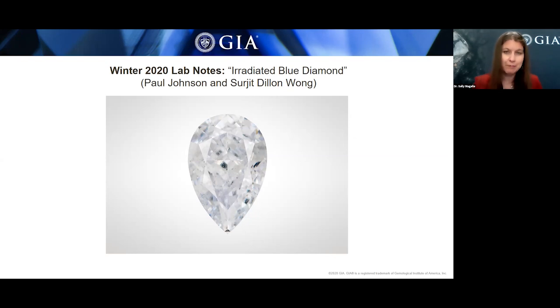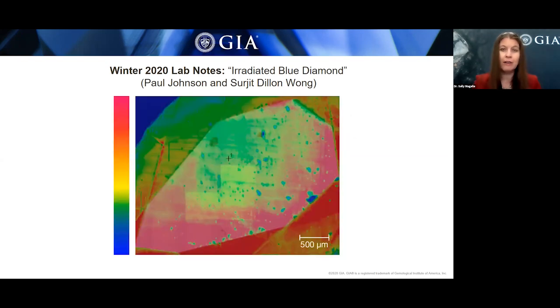This next slide shows that when it was mapped at nitrogen temperature with a photoluminescence microscope, this GR1 radiation is concentrated on one side of the table facet and on the crown of the diamond. The red areas are the false color red that's near the bottom of your screen.